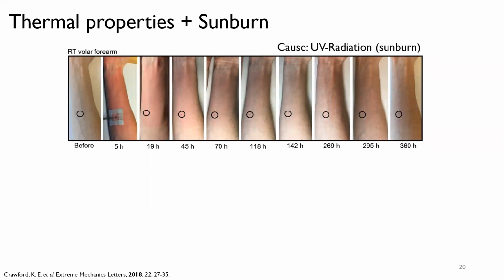And in fact, not only did we use the analytical method, but my colleague and I developed a scaling law. So we could simply put in what the estimated diffusivity is, and some of the other parameters about the device size, and we can extract out just very simply an approximated effective thermal conductivity. So the images that you see, one is a right volar forearm. That means the inside of the forearm before a burn occurs. And then the next image is 5 hours after the burn has occurred. And then you can see it gradually healing over time.